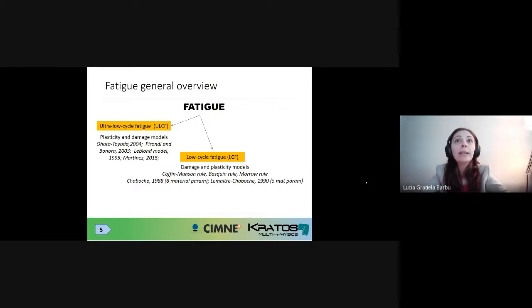Now, low cycle fatigue is somewhat more standard, or more taken into account by the industry, because we have some standard rules which are implemented in different fatigue software. For instance, the Coffin-Manson rule, which is, I believe, the most widely used, the Basquin rule, the Morrow rules. Here is an area where normally you find damage and plasticity models, sometimes joined together. And most of the models developed in this area are based on two base models, I would say, which are the Chaboche model and the Lemaitre-Chaboche model, developed in 1988 and 1990. Now, there are a lot of researchers working in this area, but a lot of the models proposed nowadays are generally extensions based on these two models.